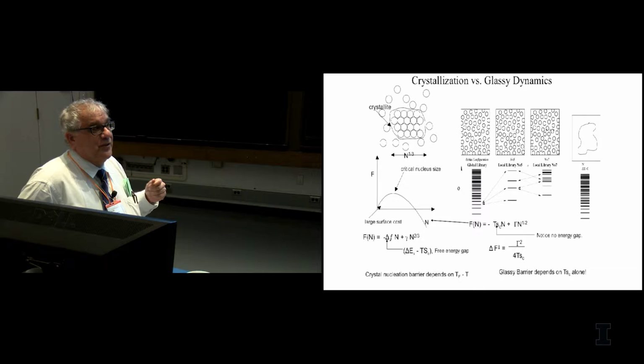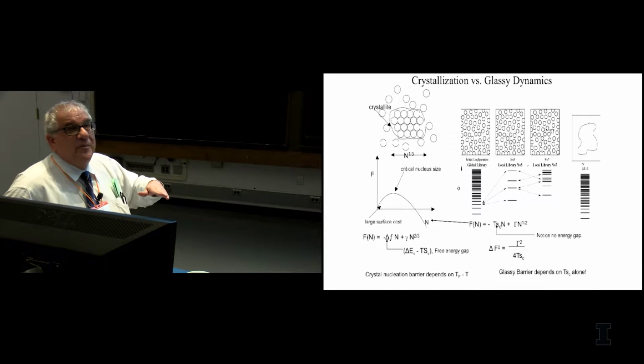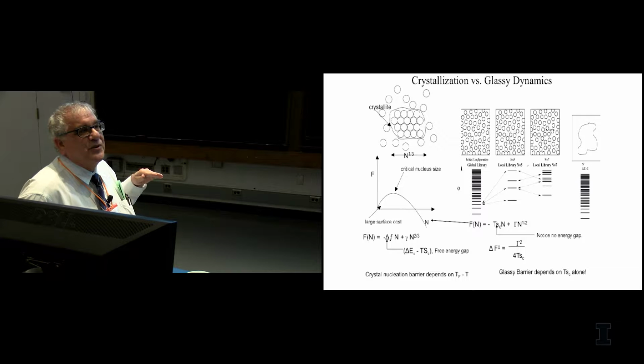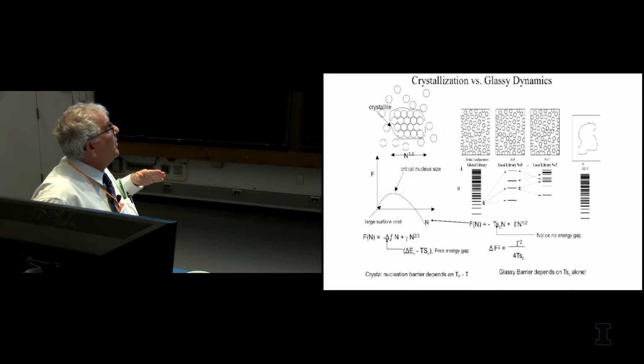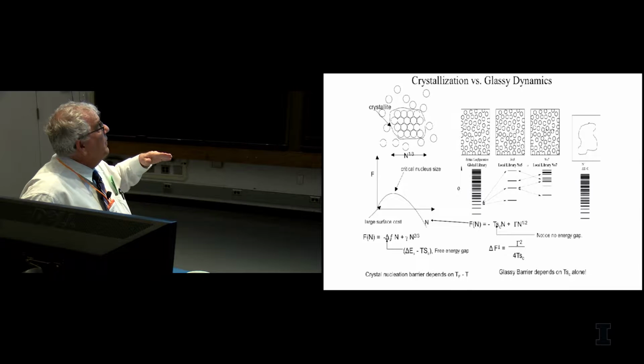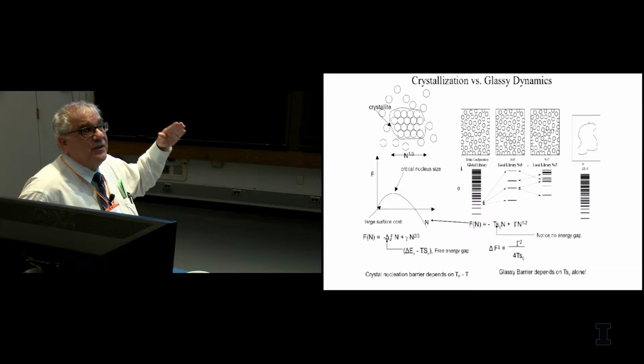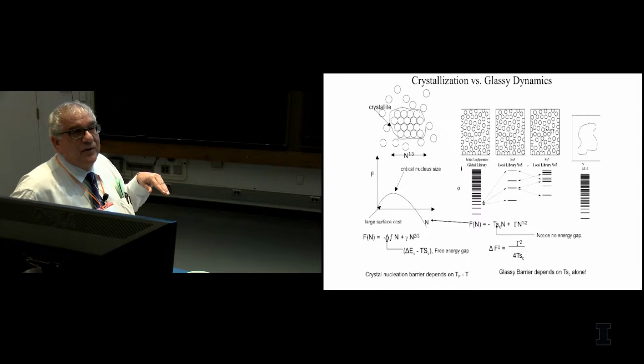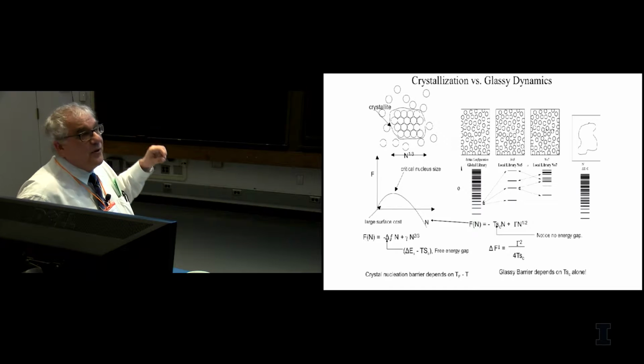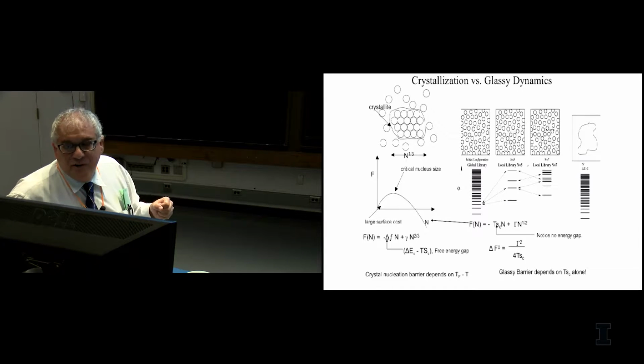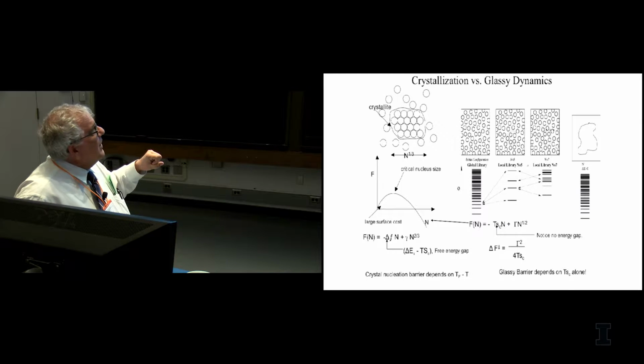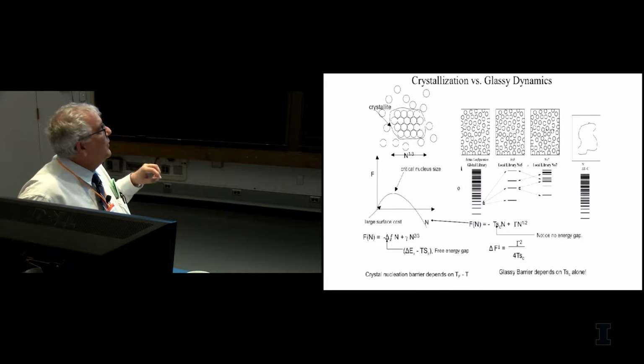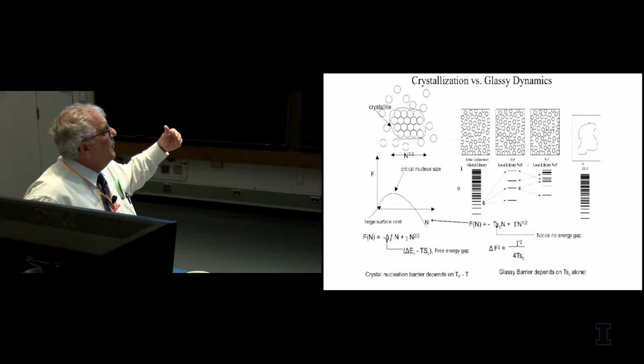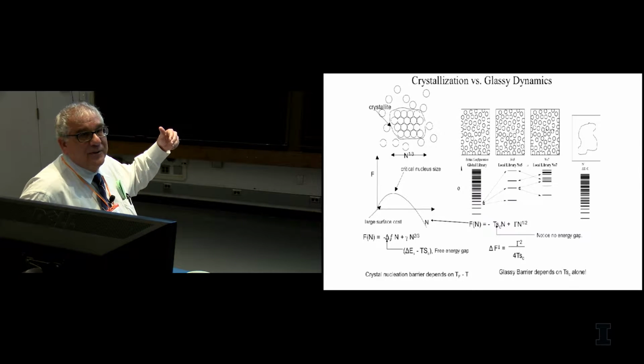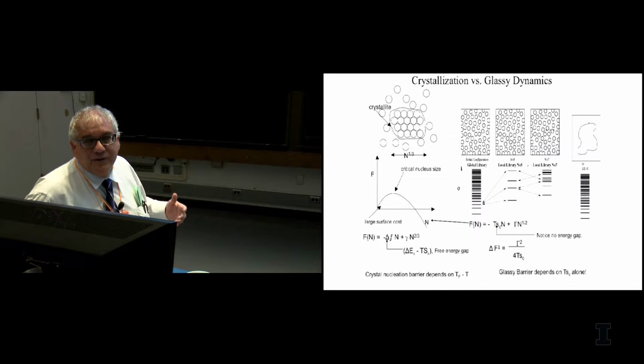What's different if you have many such structures? If you have many such structures, you'll be able to find another one with nearly the same energy that you started with. It will actually have an energy that will vary around it. But now, when you're in that particular minimum, there still is an advantage to going to some other structure because there's exponentially many, and it's an exponential number that grows with the size of the system. So the driving force to move out of any minimum is this configurational entropy. And the only other technical difference is because there's many such structures, the scaling of the mismatch term would seem to be more like n to the 1/2 rather than n to the 2/3 in 3 dimensions.